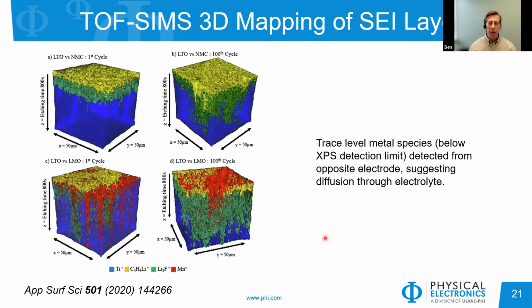We can also use TOF-SIMS to look at the SEI layer as a function of cycle times and things like that. In this case, we have a lithium titanate and, I believe, a nickel manganese cobalt material. And so we see different species at the top surface after the first cycle. And then as we continue the cycling, what we find is that there are actually some components from the manganese, the opposite electrode, that have started to migrate over to the other side of the system. So there appears to be some breakdown in the system where we're seeing different migrating species back and forth across the electrolyte. But we can also map out things like the lithium fluoride, which is the green, and how that develops with multiple cycles.